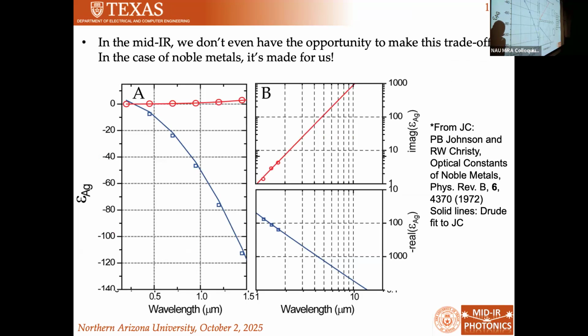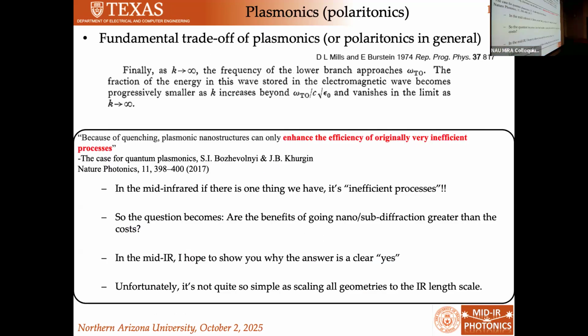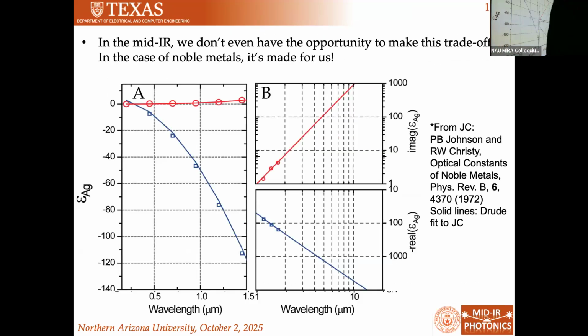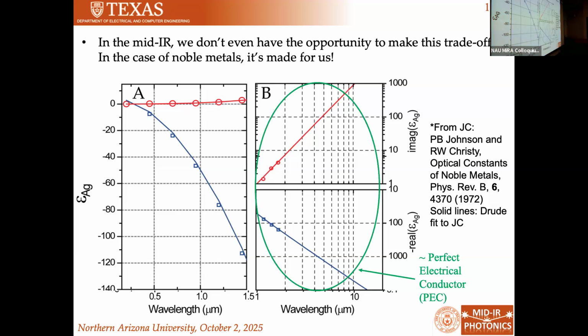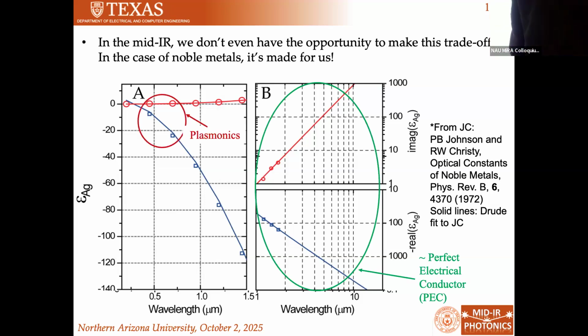Now, can we do this? So I guess there's a question here. Can we essentially make this trade-off with traditional metals? For shorter wavelengths, typically, when people do plasmonic work, they use gold or silver. In the mid-infrared, if we wanted to leverage these plasmonic modes, could we do that with gold or silver? What I'm showing here is the permittivity of silver. If you look in the mid-infrared, you'll notice that the permittivity here is quite large and negative, on the order of -100 to -1,000. And remember, all of the good stuff for plasmonics happens when the permittivity of your metal is approximately the same as the permittivity of your surrounding dielectric, but flipped in sign. So we don't have dielectrics in the mid-IR that go to -1,000. So the region where these noble metals are plasmonic is actually here in the visible.